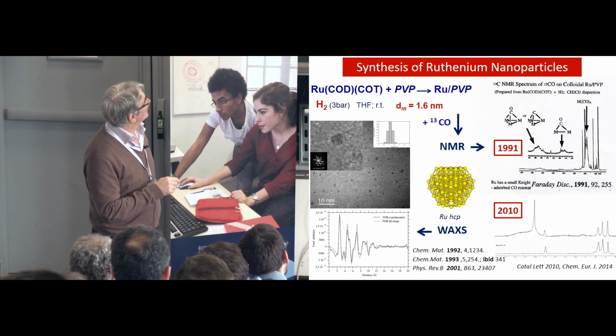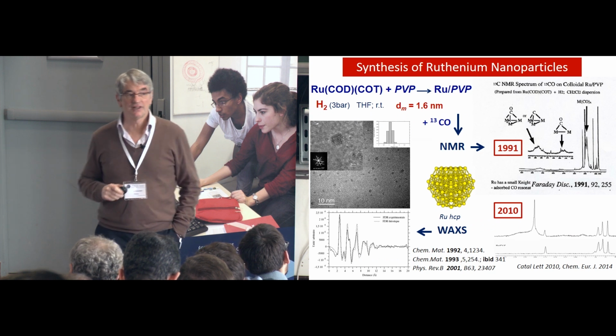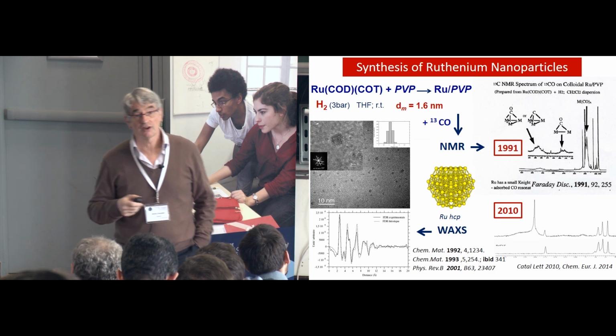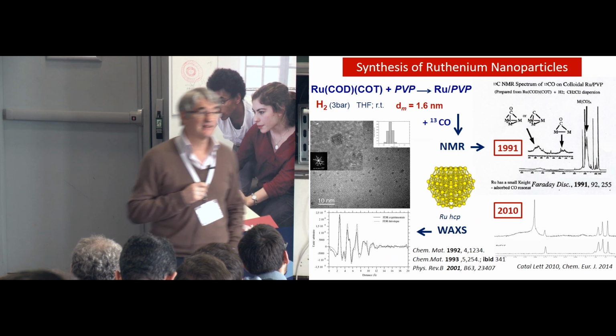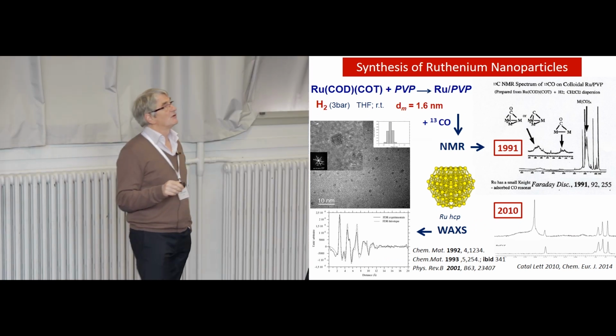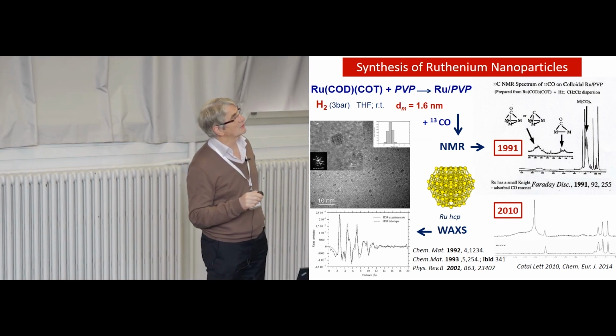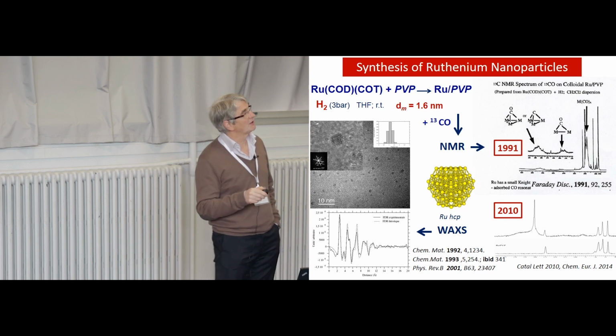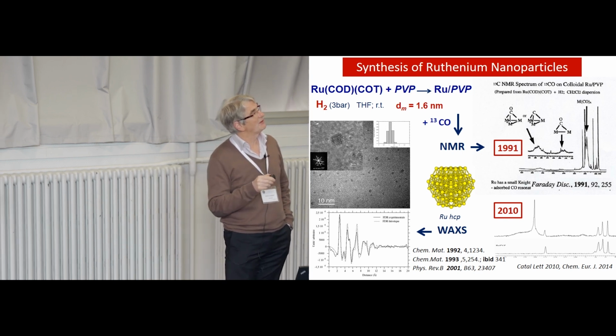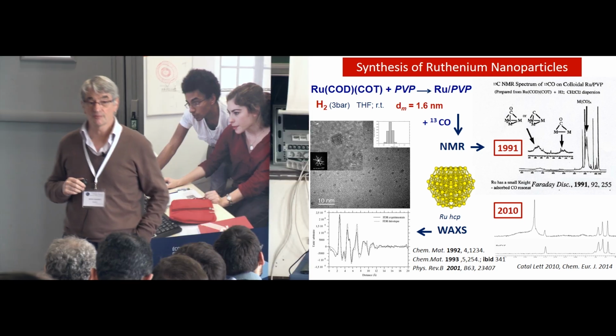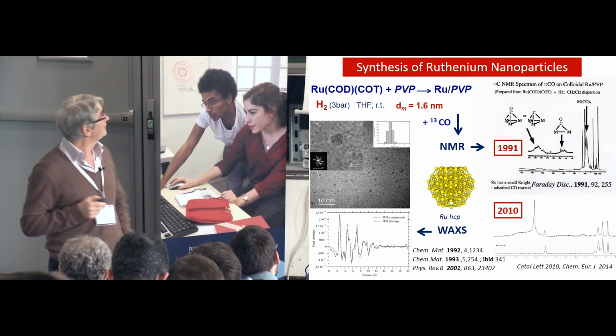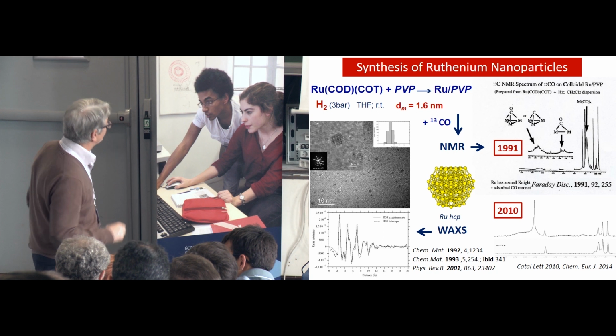So at the beginning, we used polyvinylpyrrolidone or other cellulose acetate, cellulose nitrate to stabilize the particles, and we got monodispersed, more or less, small particles. This is our first high-resolution electron microscopy from the early 90s, which was not too bad, actually.